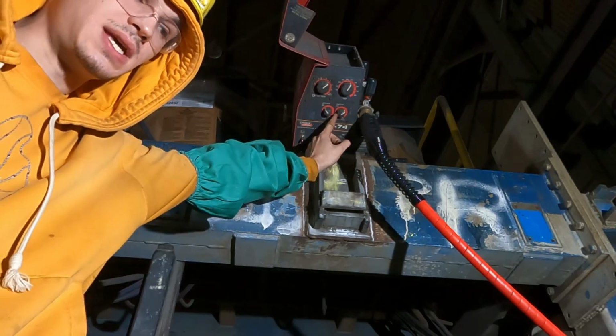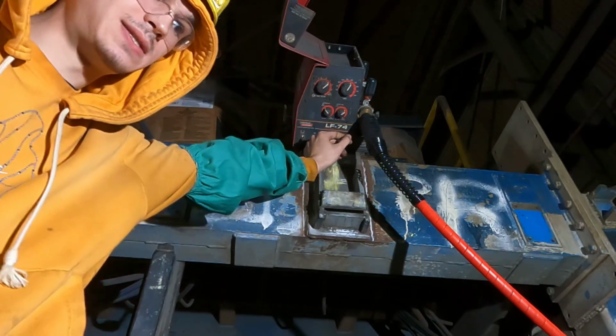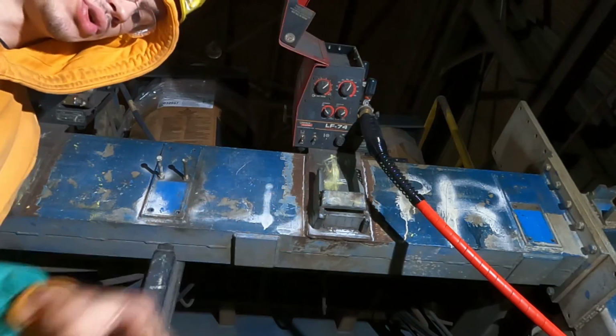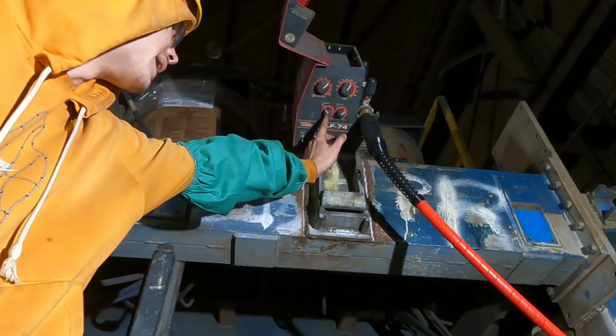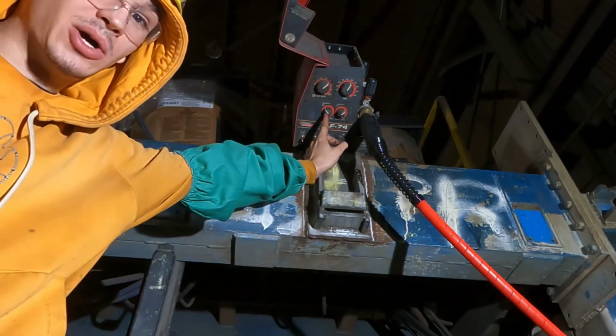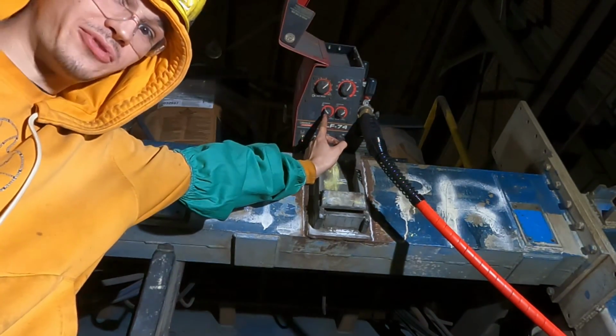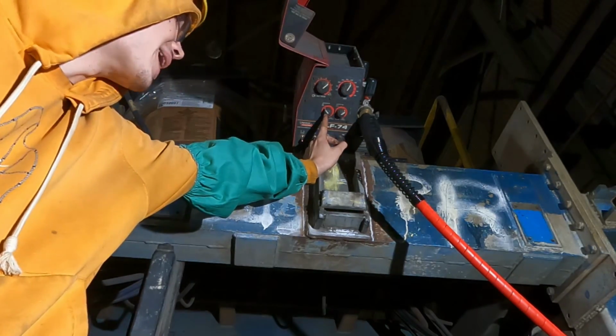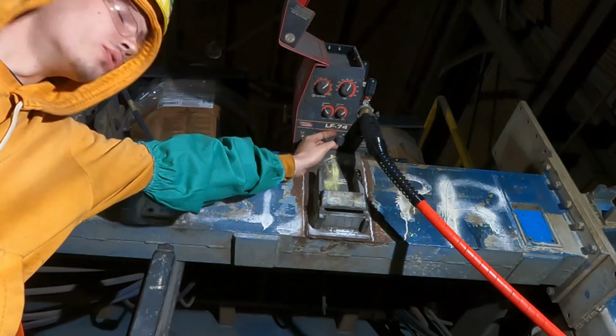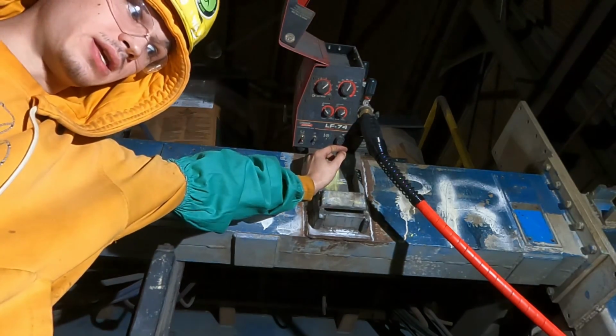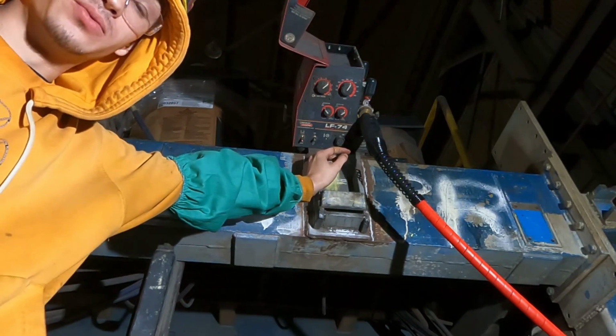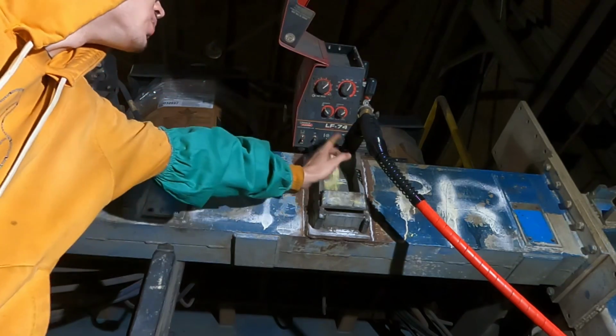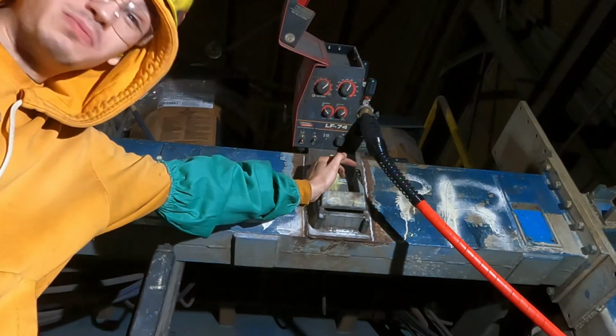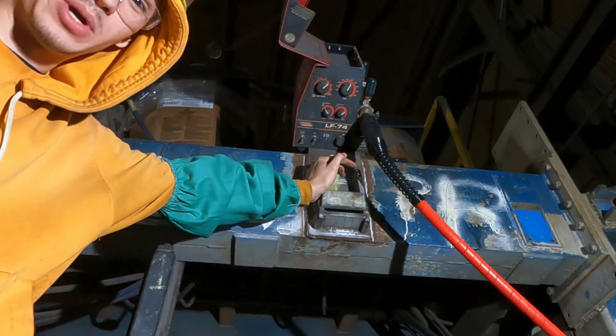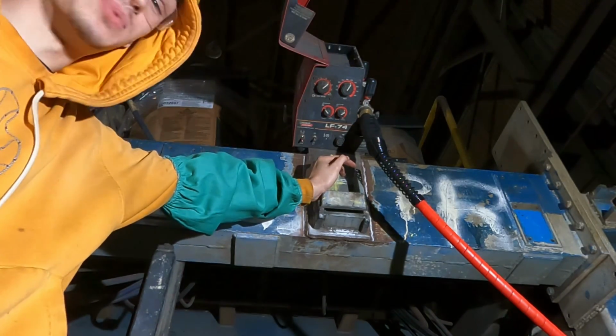What that does is that it controls how much gas continues to flow through your gun after it gets done welding. And on the burn back here, this burn back knob, you want that at about 1/4 to a half a turn. And your burn back, if you have it too low, all the way down to 0, then your wire, once it's done welding, will get stuck to the plate. But if you have it turned up all the way, then you may be going to the vending machine and grabbing yourself a brand new tip. So that's a good way to ruin tips.